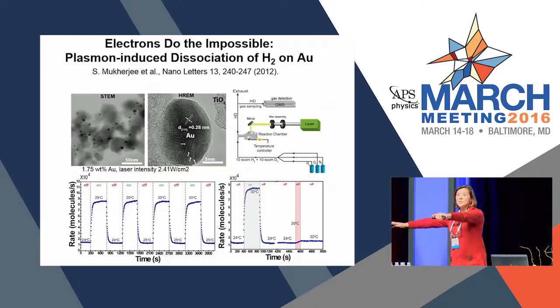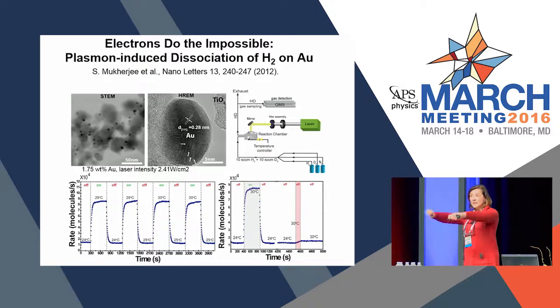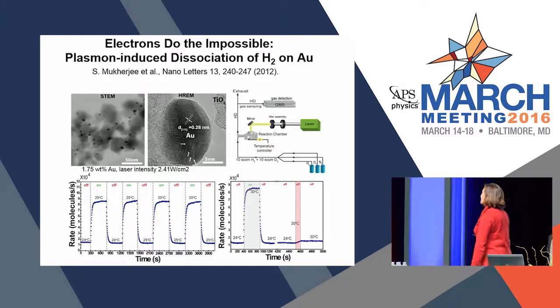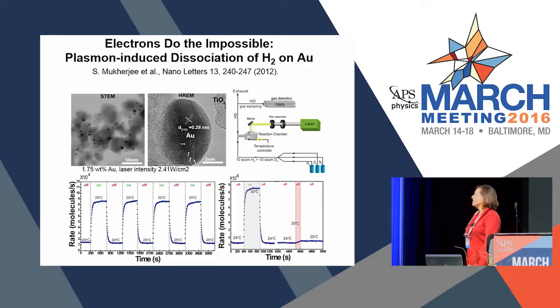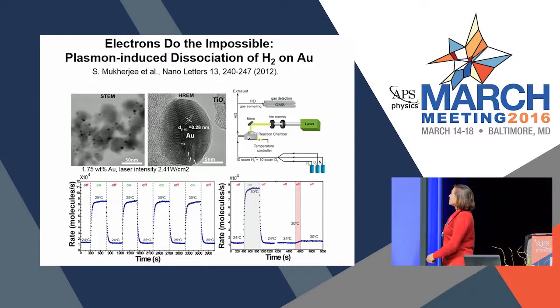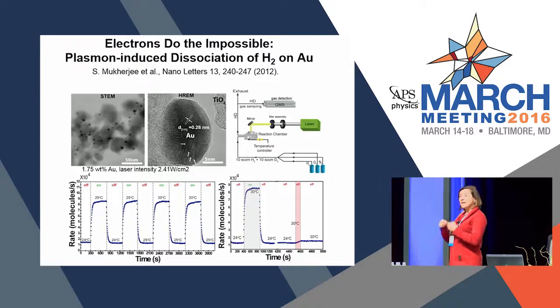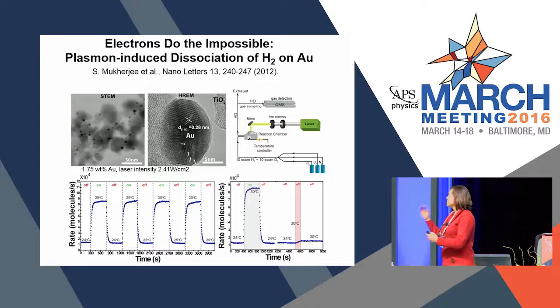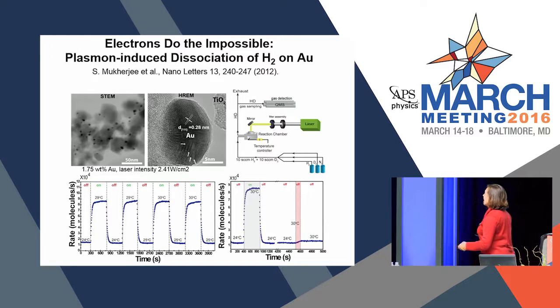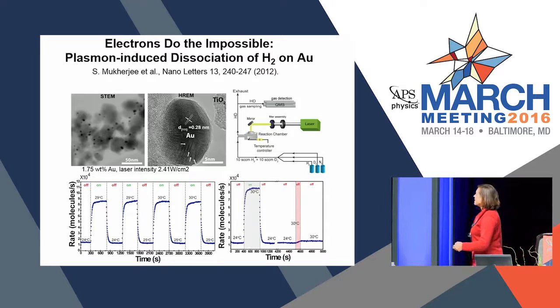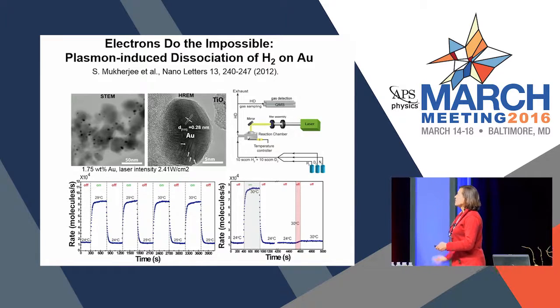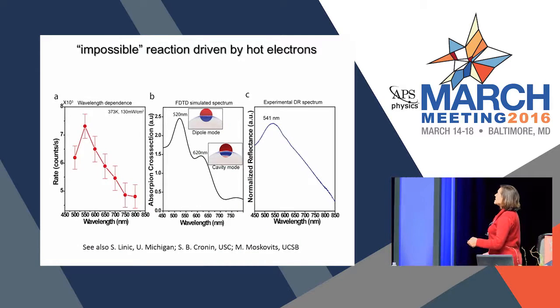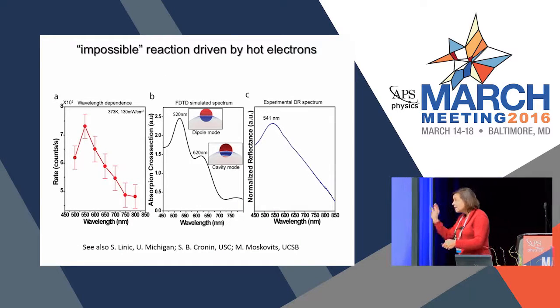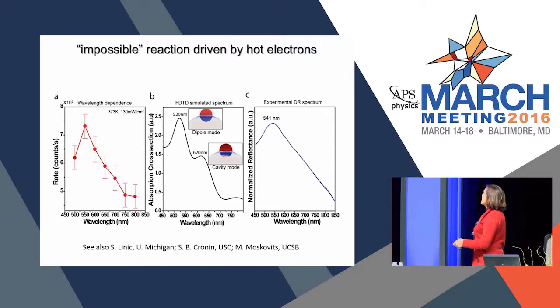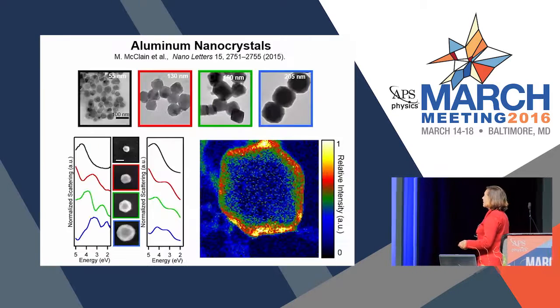We measure this by flowing H2 and D2. And so if we're going to actually dissociate the molecules, we should form HD. So I just look at the mass of the molecules when we illuminate, and when we do not illuminate, and we see that when the light is on, we're able to generate HD quite well. It's not a thermal effect at all. It is a purely light-driven effect, so it is a direct charge transfer. And we can see it actually has a wavelength dependence that's directly related to that resonance of the gold nanoparticle that I showed you earlier.